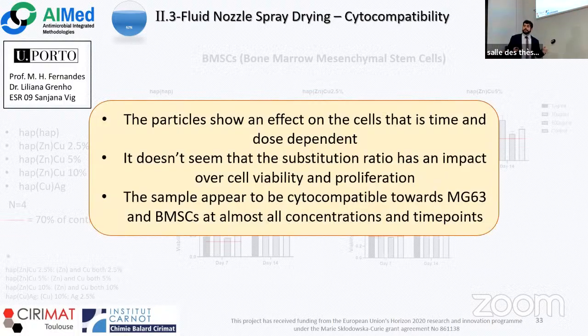So we can assess that these particles in almost all the conditions were cytocompatible, and that they can show an effect on the cells that is time dependent and dose dependent. And nonetheless, what is very, very nice for our characterization purposes, it doesn't seem that in this case the substituting ratio has an impact on the cell viability and cell proliferation.